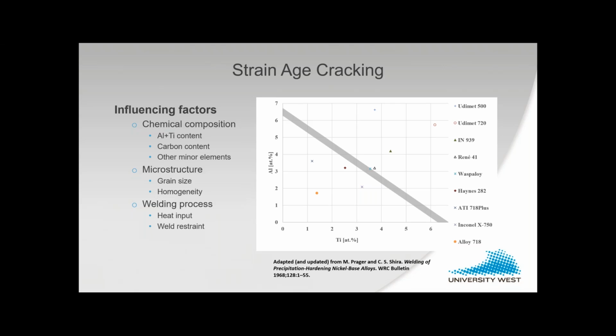In terms of microstructure, grain size is the same as for hot cracking. Smaller grain size is usually beneficial because you increase the grain boundary area, which puts less demand on each grain boundary. Homogeneity, for instance, castings are usually more susceptible compared to wrought materials. Welding process, the more heat input, the more weld restraint you have, the worse it gets in general.